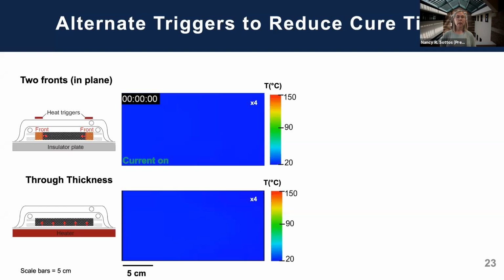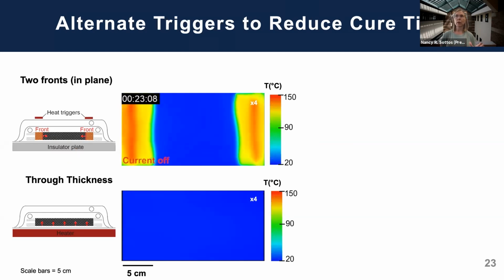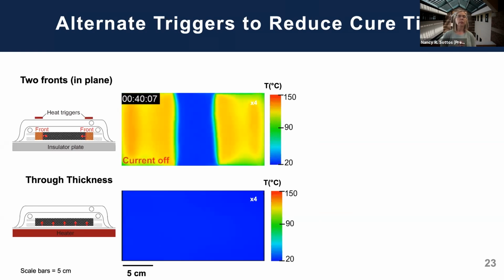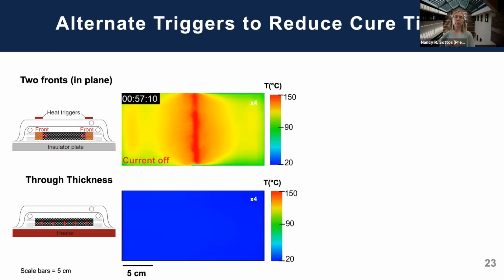We've studied two fronts, and this is two fronts in the plane. So as you can see, it's triggered from either end of the panel. They're going to meet in the center, and I'll play that video. You can see the current's on. It's triggered, then the current is off, and these two fronts will come together and merge. You'll see there's a bit of an exotherm when they merge. And this is something also that we have to manage and that we've looked at how to minimize the effects of a merging front.